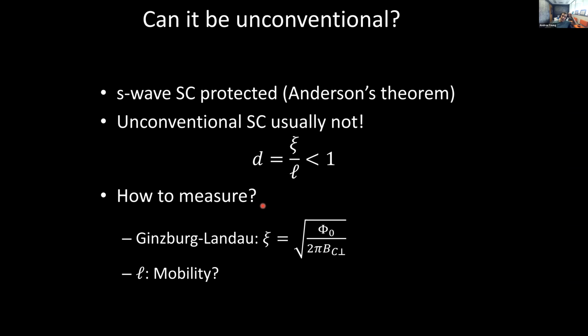And usually this is not true in unconventional superconductivity, where, for example, in a P-wave superconductor, conventional disorder behaves like magnetic disorder in a conventional superconductor. That's basically described by Abrikosov-Gorkov theory of disordered superconductors, where you don't need magnetic impurities, you just need regular impurities. So you can assess whether it's plausible that this be an unconventional superconductor by asking, what is this parameter? That's the ratio of the coherence length to the mean free path of the normal state. If this coherence length is much smaller than the mean free path, then you could have an unconventional superconductor. But once they get to be comparable, the expectation is any unconventional superconductor would be destroyed. So we can already test the hypothesis that this is an unconventional superconductor. We could negate it by simply finding that superconductivity survives into the dirty limit.